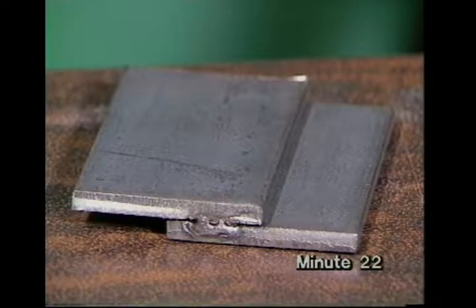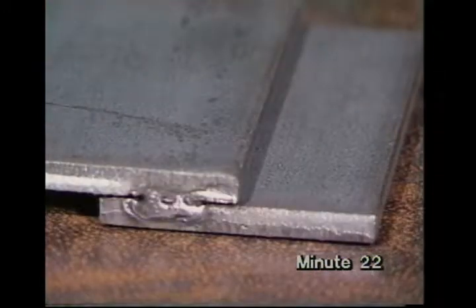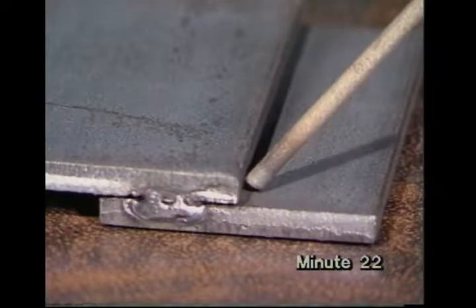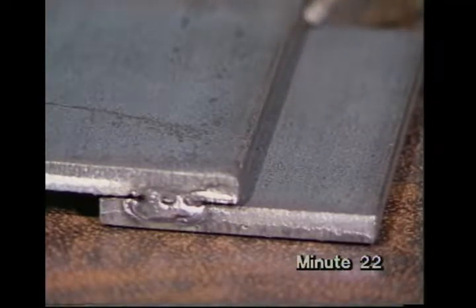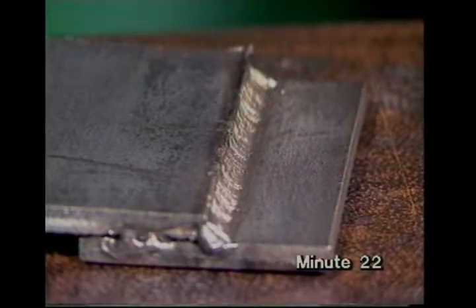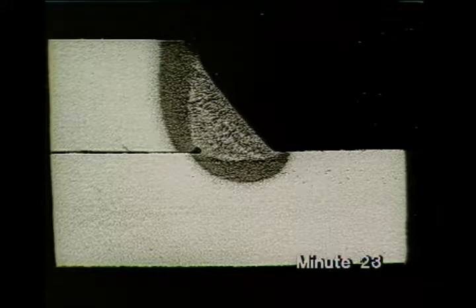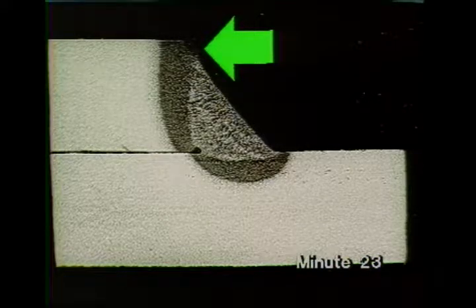Next, a lap joint. You should tack weld this on the ends. Aim the electrode at 45 degrees to the vertical into the corner, as you did for the T-joint. Try to put down enough weld metal to just fill up the angle. The macro section shows that the weld has just reached the top corner of the upper piece.